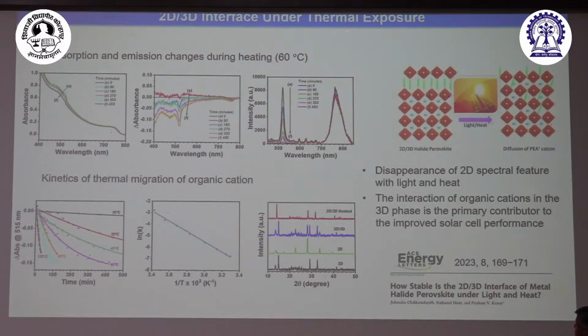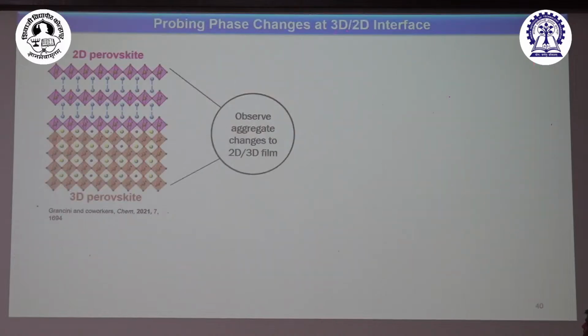And then under heat, we see the same thing: a decrease in absorbance and a decrease in emission. So the 2D layer that is there on the surface is getting mixed with the rest of the 3D. It's no longer staying as a 2D. Although in the beginning, in the cross-section TEM, they show a nice 2D layer, it no longer exists. So these cations are all diffusing in. Okay, we observe aggregate changes in the 2D film; how do we probe the individual transformation?